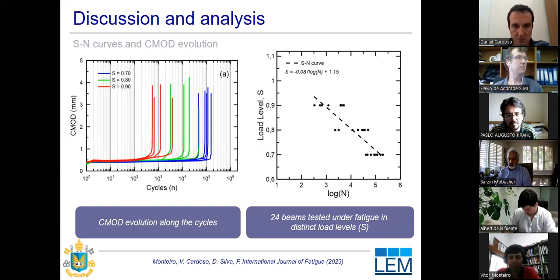So one of the first results we have for the beams under fatigue was the evolution of the CMOD. It's possible to verify, for all load levels, an almost linear increase in CMOD until reaching around 0.50 millimeters of CMOD. Then there is a sharp increase in the CMOD rate until the beam reaches its fracture.